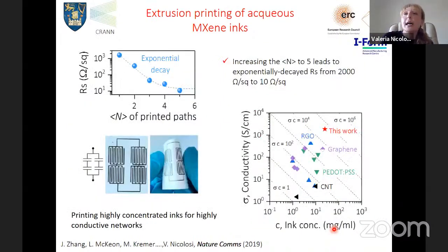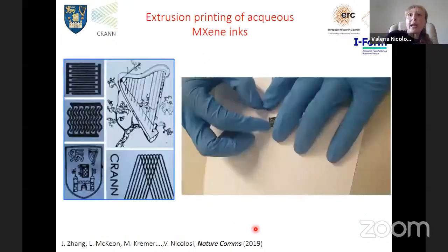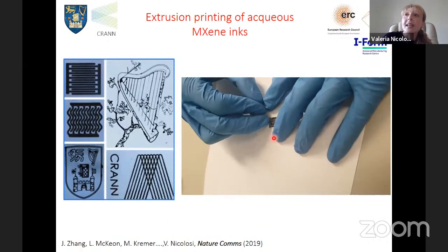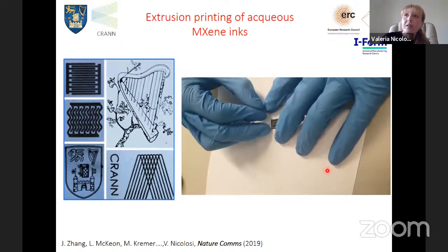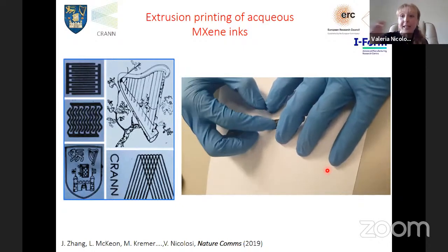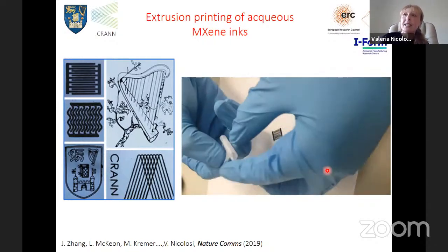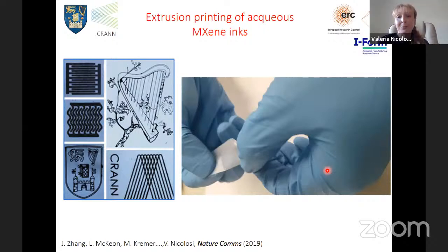And if you go on to performance, again, we can decrease the resistance massively by printing more layers. We can reach very high conductivity by printing more layers. And you can print these devices in series, in parallel. The freedom of printing devices is that you can really print the device in the configuration you like. What I show here also is how resistant these devices are. Here we used Scotch tape to try to peel off the ink from the piece of paper after we printed, and indeed there is no residual at all. Once it's printed, it's nice and stable.